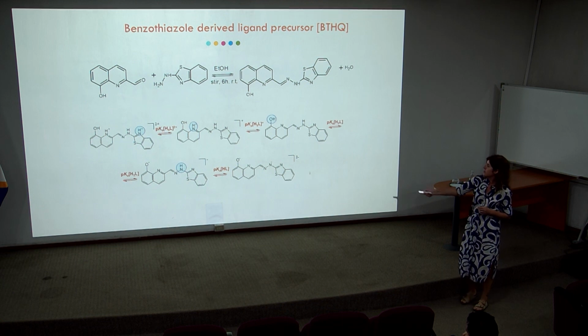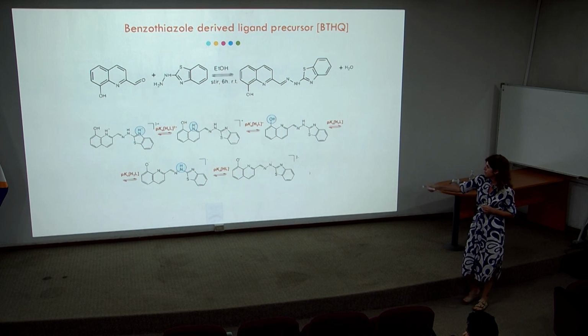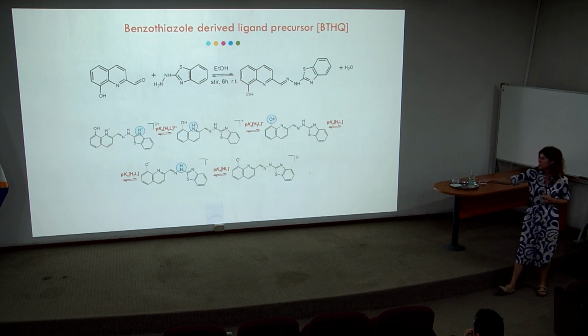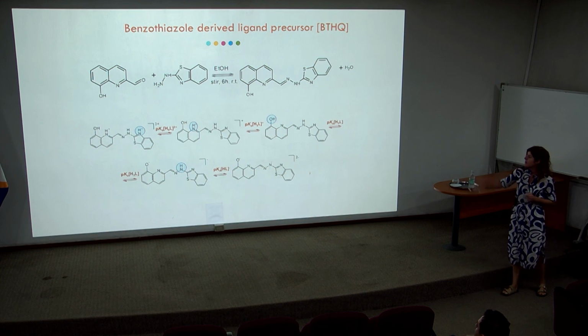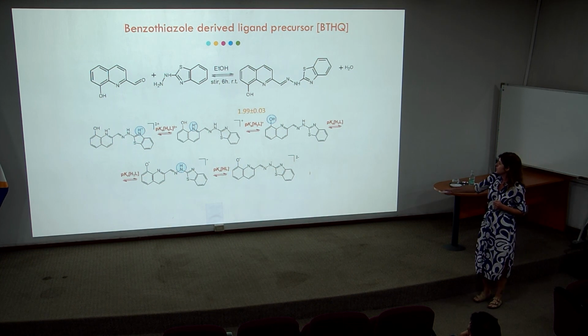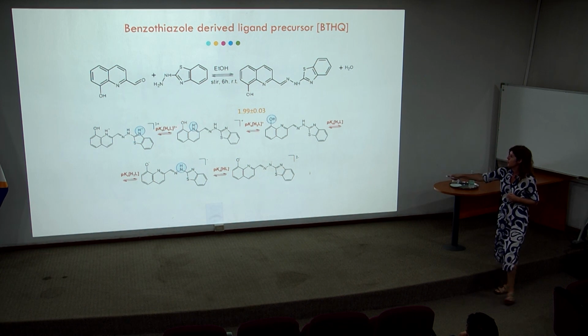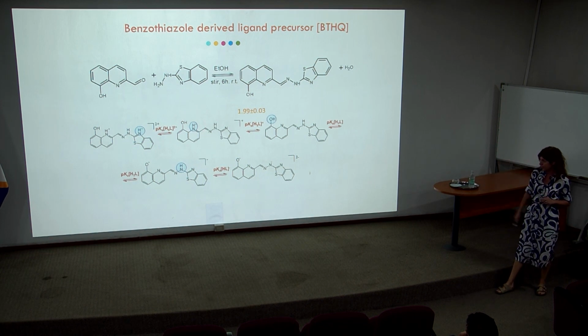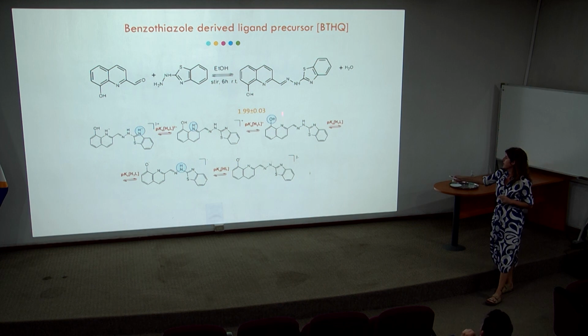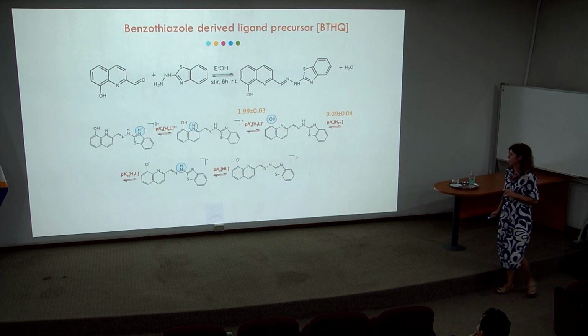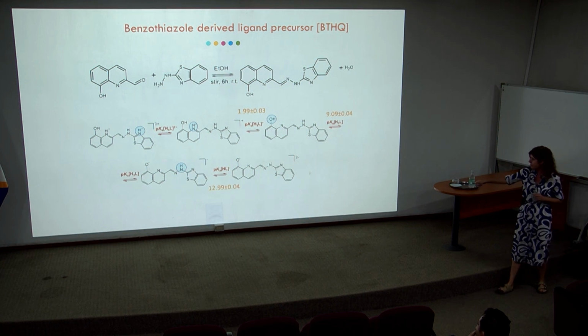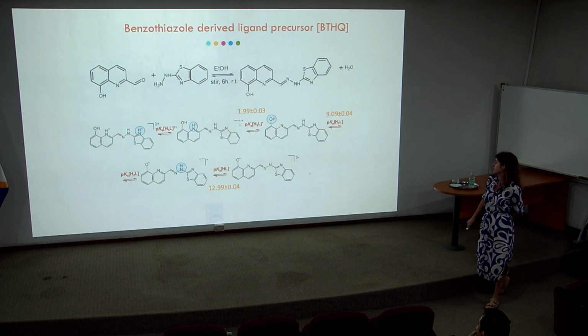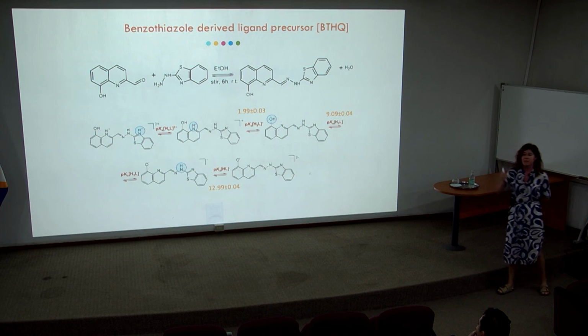We could not determine the pKa value for this proton here, but we could see that the first proton to go out is the one from the quinoline nitrogen, then the phenolates in the usual pH range, and in the end, this proton.